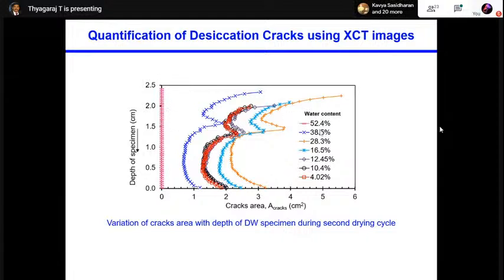As the water content changes, you can see it increases; this red one at 28.3% is where the crack area is maximum. Then as the water content still decreases, the crack area decreases again, and you can see this is the crack area at 4% water content. Why is it so? Initially the sample shrunk, and because of the global shrinkage of the sample, the crack volume has reduced. Crack volume increased with the water content, then decreased. That you can clearly see.